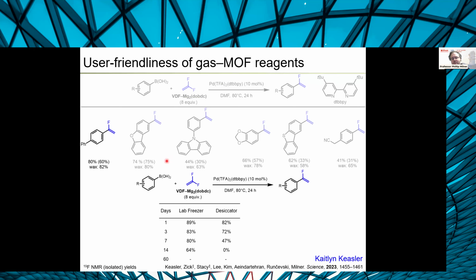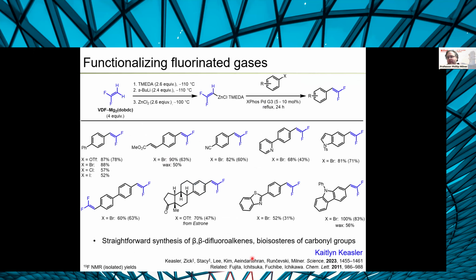And these gas-loaded MOFs are actually quite stable here. So we found that if we kept them cold or left them out in air, they do slowly lose the gas. But if you look at these capsules here, they actually don't lose the gas even after 60 days. So you can really think of these as just a little cylinder that sits on the bench top loaded with gas. I'll just show you a couple more transformations we have found using these gas releasing reagents here.